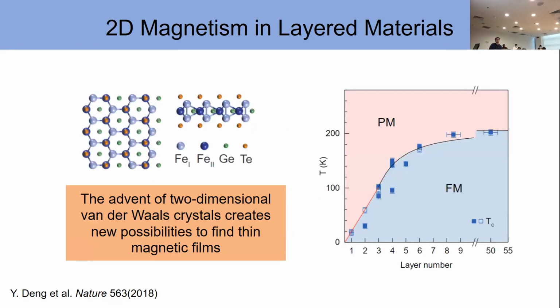And I would also like to introduce 2D magnetism in layered materials. Finding magnetic films with thinner thickness is a goal for the magnetic physics area. Recently, with the advent of two-dimensional van der Waals crystals, which can be exfoliated down to a single atomic layer, we are given new possibilities to find such thin magnetic films. What I show here is iron germanium tellurium, and it still persists in ferromagnetic order down to a single layer.